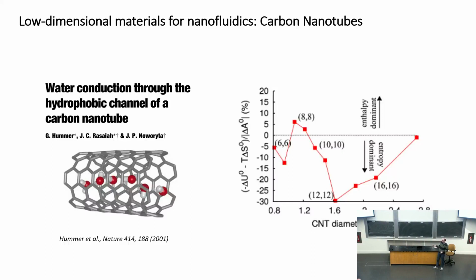In terms of the driving force, though, it really depends. Why does water actually want to go in there? Depending on diameter, the answers are different. So in a big chunk here, it's actually entropy-dominated. Water, when it goes into the CNT, actually gains a lot of freedom to rotate, much more than in the bulk, which is a driving force to actually put it in. But it actually varies, and this is a suggestion of why it actually fills.